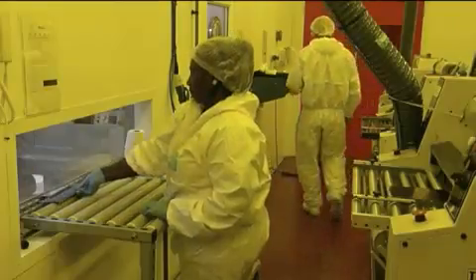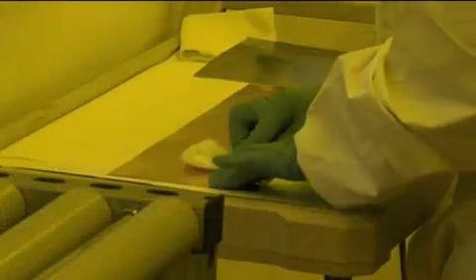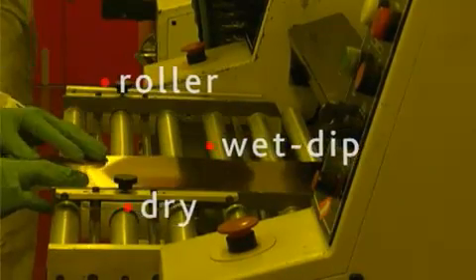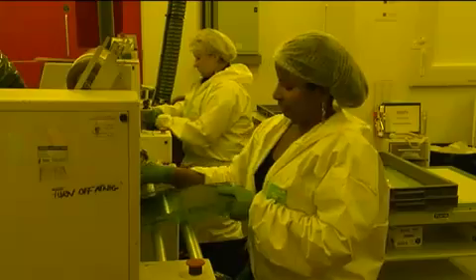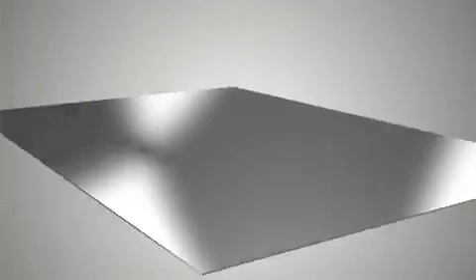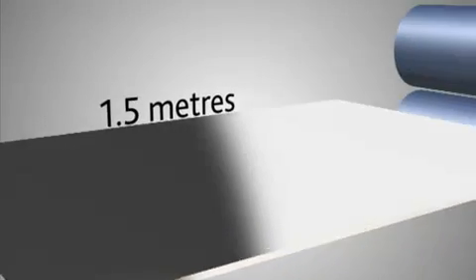The photo etching process can be achieved through a number of different lamination methods, including roller, wet-dip, or dry lamination. This comprehensive range of approaches allows component manufacture from metal with thicknesses of 10 microns to 2 millimeters, and in sheets of up to 1.5 meters in length.